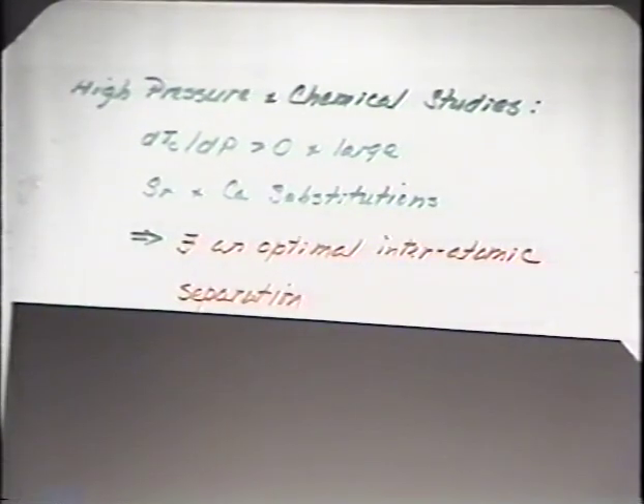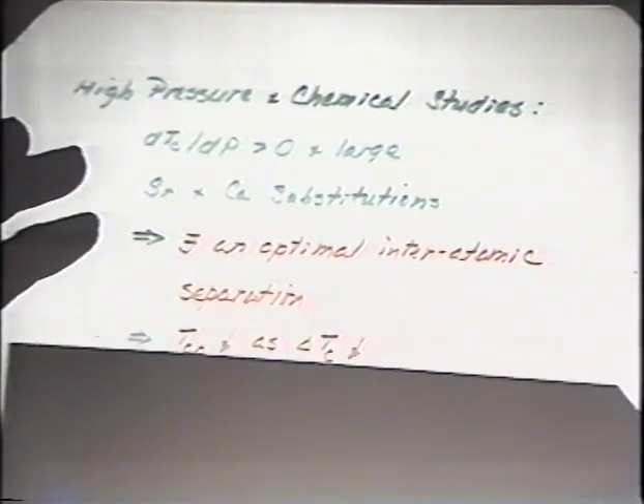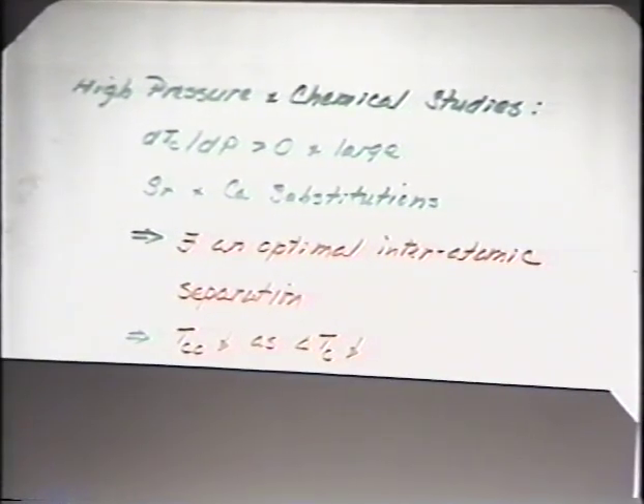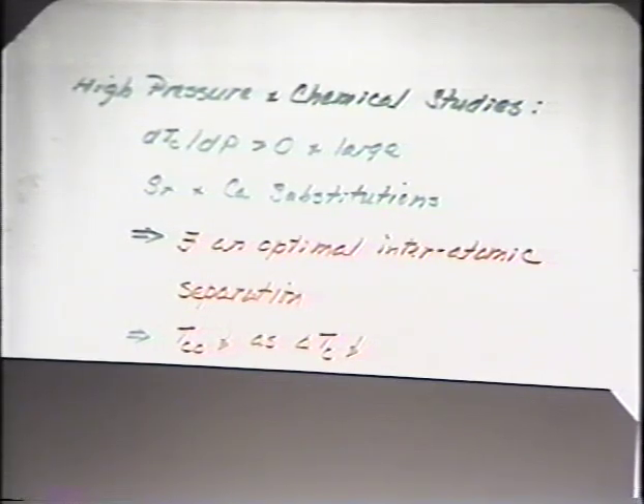Immediately the TC went up with the application of pressure. We thought that just by squeezing it, the TC would go up much, much higher. But unfortunately, when we replaced strontium with calcium, which has an even smaller atomic radius, the TC goes down. So this tells us there exists an optimum interatomic separation for high TC. And then the other hint, by the beginning of this year or the end of December, we had accumulated quite a bit of data.